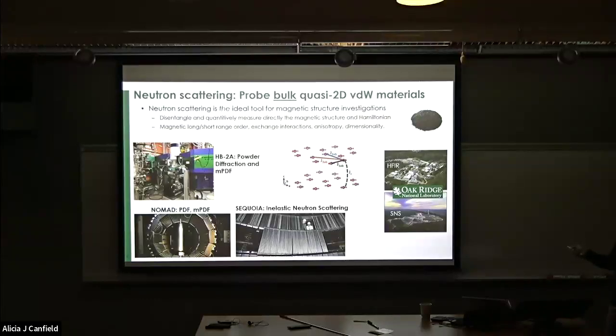So like I said, everything's on a powder. I'm going to present results taken on these three different instruments at Oak Ridge. So the HB2A instrument is a powder diffraction instrument at HFIR, the reactor source, where you can see it's quite an open instrument, so it's quite flexible to have a variety of different sample environments put in there. You can get to high fields, low temperature, high pressure, and so forth.